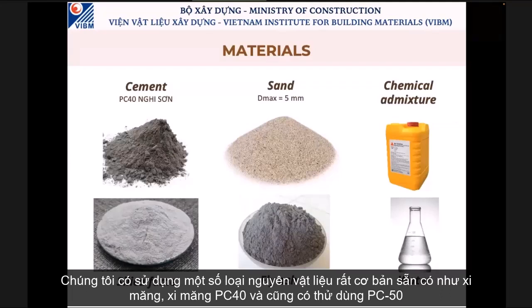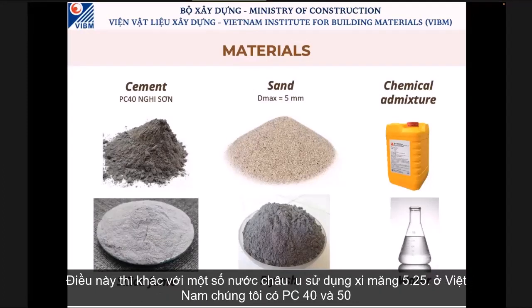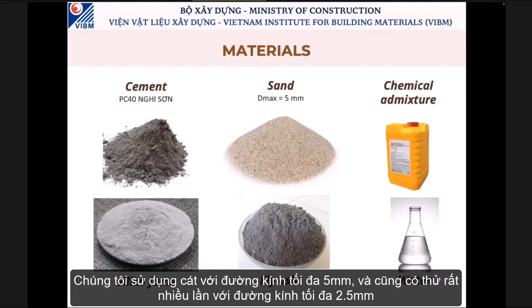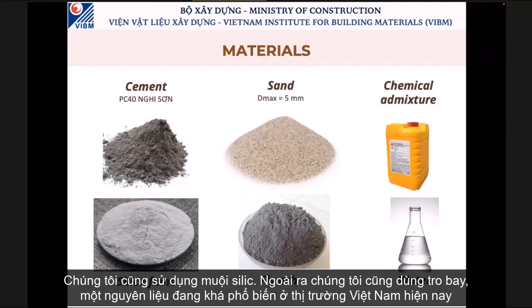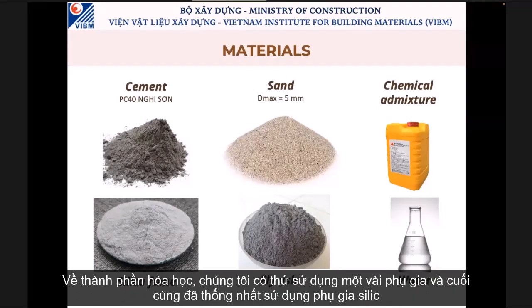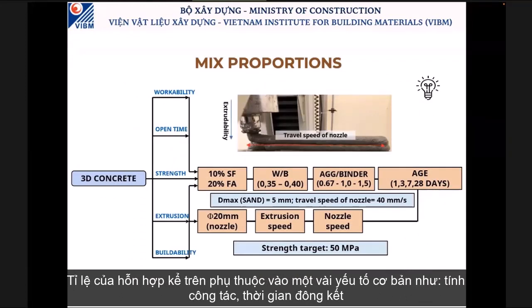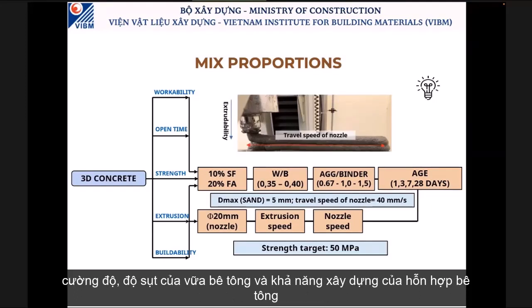We use some very available normal raw materials, including cement PC40, and we also have PC50. Different from other countries, like in Europe, where you use 52.5, in Vietnam it is 50 and 40. We use sand with a maximum size of 5 millimeters, and we also tried a lot with a maximum size of 2.5 millimeters. We also use silica fume, and fly ash, which is in very large volume in the Vietnam market now. And for chemicals, we tried some different admixtures, but we came up with one of the Sika admixtures. So the mix proportion is optimized based on some very basic criteria: workability, open time, strength, extrusion, and durability.